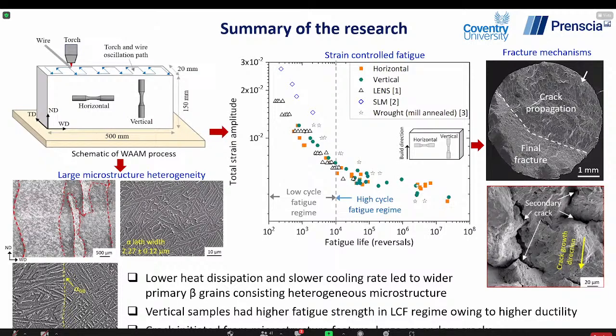If we look at the WAAM Ti64 data, we can observe the influence of primary beta grains and this microstructure heterogeneity on the overall anisotropic behavior, where vertical samples showed a marginally higher strain control fatigue behavior when the applied strains are within the low cycle fatigue regime. However, we don't see much difference between the horizontal and the vertical samples when the test data is in the high cycle fatigue regime.